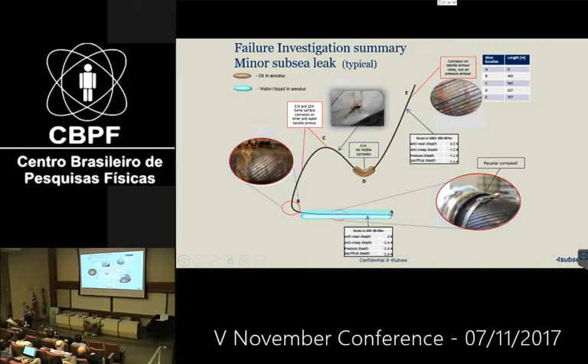And it's fair to say that very many flexibles, I don't know the exact percentage, but it's high, suffer from an outer cover damage during their service life. And flexible pipes are designed for operation with a water-filled annulus. But there are some assumptions made in that, and that's been discussed widely here today. We assume that it's a confined environment, and we then build up a reliable protective film to protect against CO2 corrosion. And when it comes to oxygen corrosion from seawater, we have a CP system which protects the exposed wire surfaces. So we rely on those two systems, and generally speaking, they work, but not always.